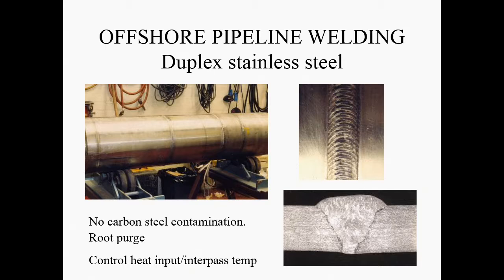Now with duplex stainless steels, it's almost the opposite. You don't want very slow cooling rates. Can you guess what that is? What happens in stainless steels if they cool down very slowly? Remember that in our introduction we had a graph with the time required for some harmful carbides to precipitate in stainless steels. Remember that? If the cooling from high temperatures to low temperature takes a very long time, then we have a very long time which is ideal for these carbides to precipitate.